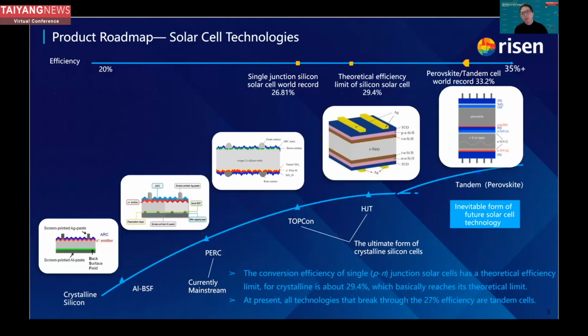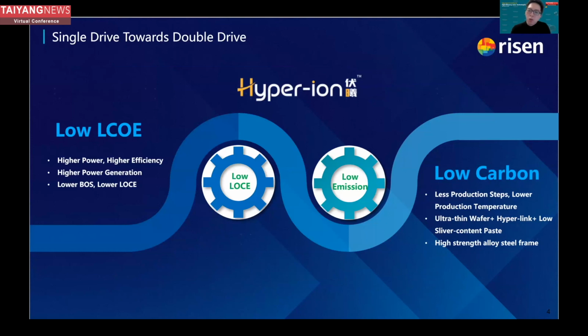And why did Risen firmly choose heterojunction technology as our key technology? Because we have studied all the PV technologies. From today's mainstream PERC, which has reached its bottleneck of 24.5%, as is known to all, and the emerging N-type technologies, TOPCon and also heterojunction, with efficiency potential up to 28.5%. And there is also the next-generation technology, the tandem cell, which can combine perovskite together with heterojunction, TOPCon, or other technology, which has potential up to 45% or even higher. And by comparing these technologies, we found out heterojunction is the product with the greatest potential to realize our